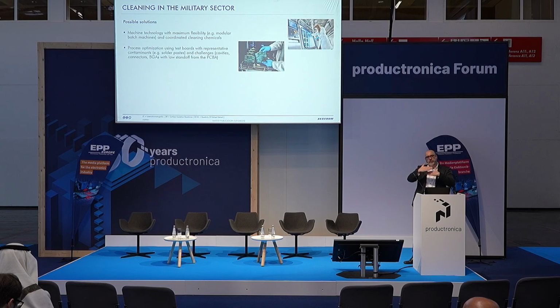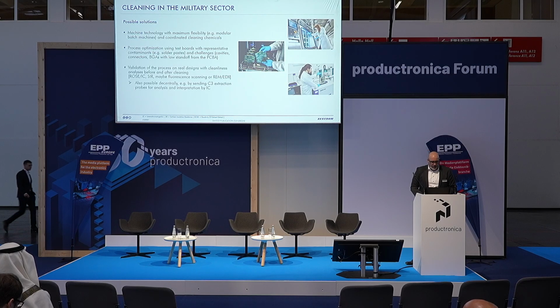So that means that the solder pastes that are typically used are used on the test PCBs, that you have ICs, for instance, that represent the size and the standoff, which is the difference between the PCBA and the underside of the microcontroller, for instance, so that this is represented properly on the dummy board, and also connectors that are, for instance, cleaned, or other devices that might be critical, so that these test boards are really representing, let's say, the critical points of the final design.